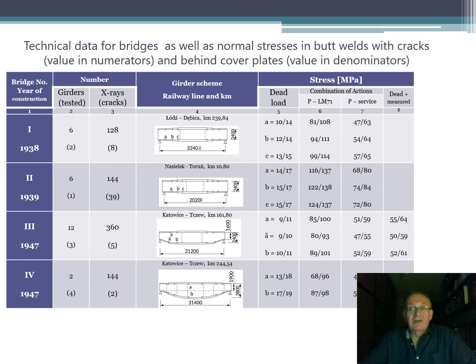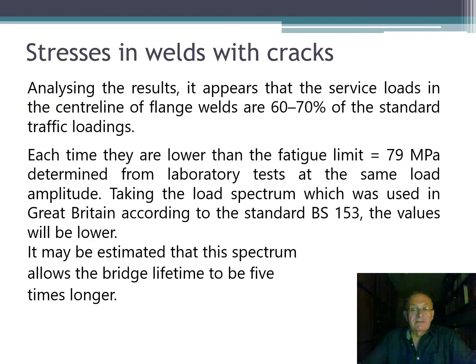Of course, the stresses were also calculated for that load, for a combination of factors with standard loading and with service loading. As you look at the stresses, they are not so high, so it was good for the structures. Analyzing the results, it appears that the service loads in the center line of the flange weld are 60 to 70% of the standard traffic loads. Each time they are lower than the fatigue limit of 79 megapascal determined from laboratory tests at the same load amplitude. Taking the load spectrum which was used in Great Britain according to the old standard BS 153, the value will be lower. It may be estimated that this spectrum allows the bridge lifetime to be 5 times longer.